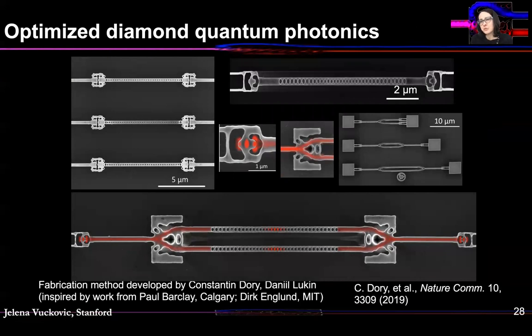So how do we plan to go about it? Well, we have to rely on optimized photonic structures connecting your homogeneous qubits. We've been doing that both in diamond and in silicon carbide. In diamond, we are using our inverse design approach combined with a diamond fabrication method, relying on isotropic and anisotropic etching that was first developed by Paul Barclay in Calgary. We adopted and developed it further. This is essentially three-dimensional carving of diamond blocks, which allows you to fabricate any types of structures that are optimized for a particular function.